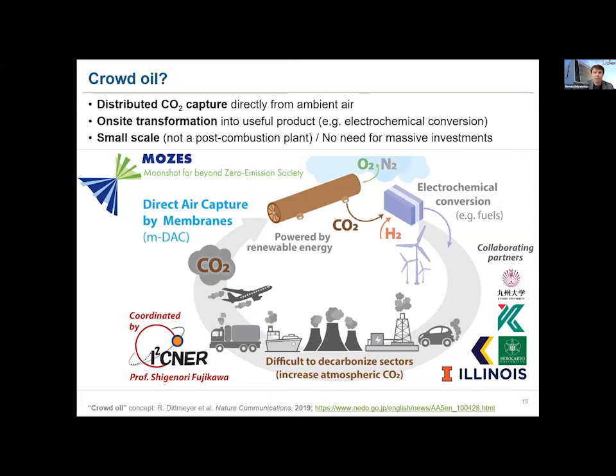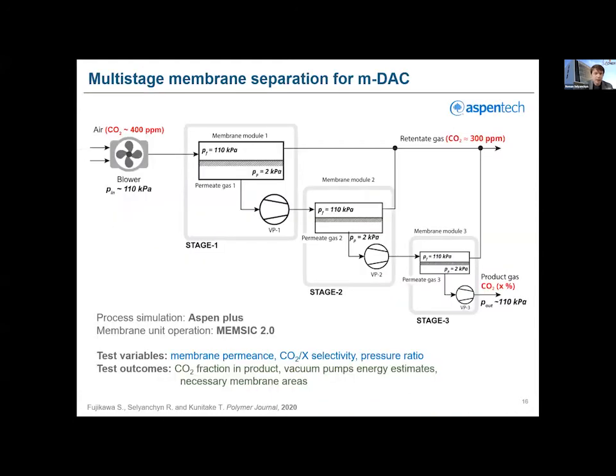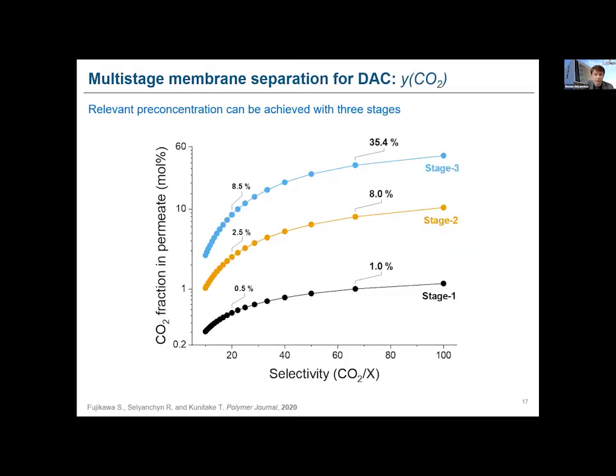And just to give you an idea of what the membrane system is expected to be, we recently conducted a process simulation study using the well-established environment based on Aspen Plus and a membrane unit operation programmed by the University of Lorraine in France. And what we found is that for the necessary level of preconcentration, one will need at least 3 stages of membrane separation and membrane with specific properties.